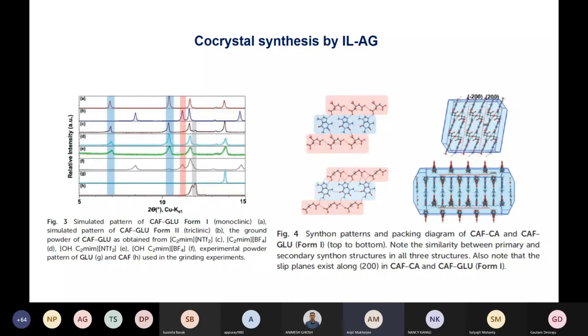And what we observed is that there are slip planes there. When you use the hydrophobic ionic liquids, slip planes are mostly non-polar, so they stick to those planes, and it shows the similarity between the two. So by this study, we showed that ionic liquid can be used as a grinding solvent in addition to the polymers which have been used earlier. And this type of study may help in extending the methodology beyond the status quo.